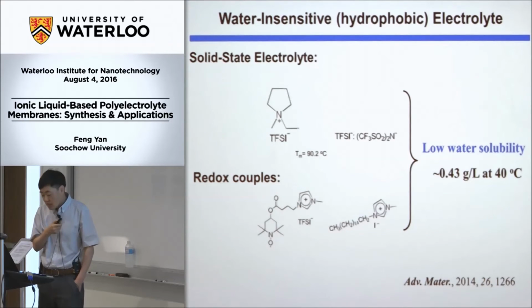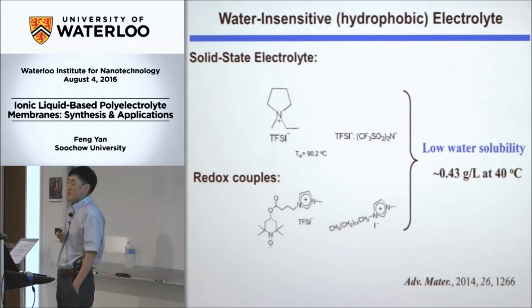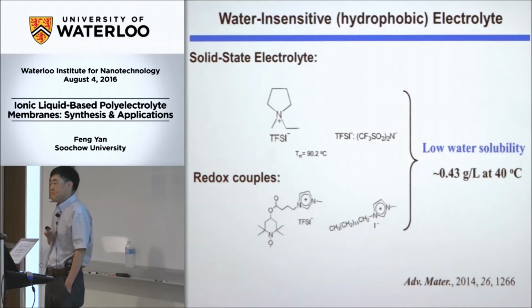We tested, but I don't remember the results. We can check later. Because that's quite important for avoiding polarization of the cell, of course. Iodine is effectively a redox mediator. If your redox mediator has a slow diffusion, then you're going to get cell polarization. Yes, yeah. But you don't know.